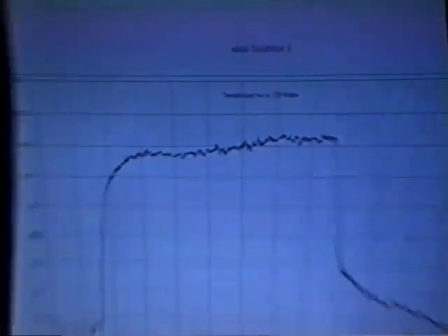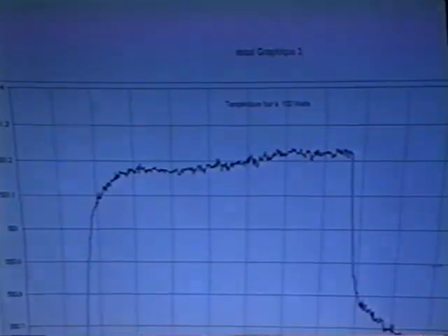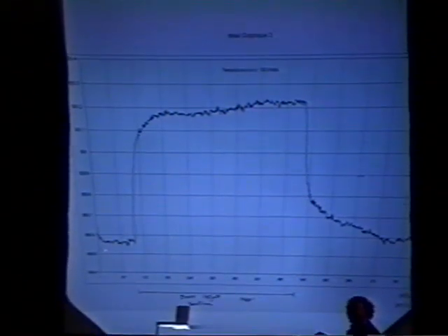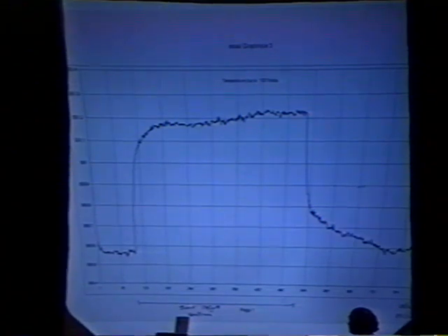Now, what we do, in that case, we put 100 watts in the furnace, and we're capable of measuring 100 microwatts. I'm trying to beat Professor Fleischmann, he was talking about microwatts, so we're doing the same. Now, at that point, we turn on a DC current through the crystal. In that case, it was 900 volts, continuous DC current. And the temperature rises very quickly. This is just Joule heating.